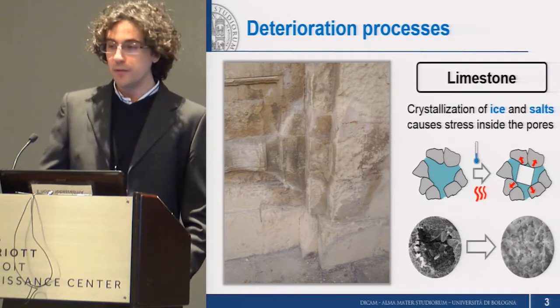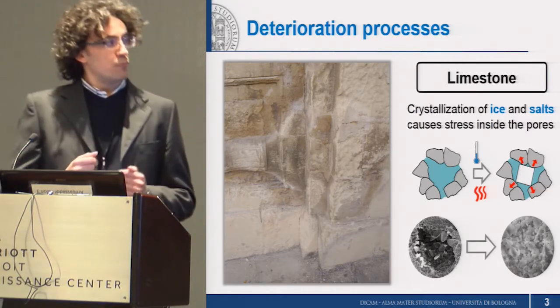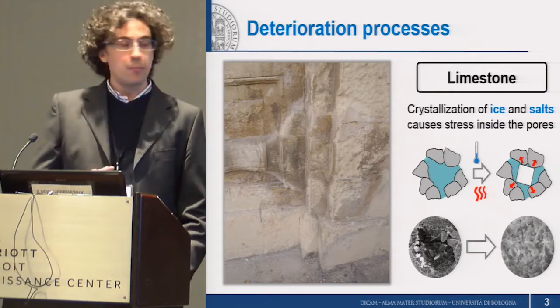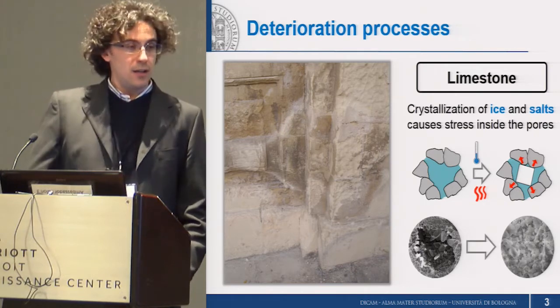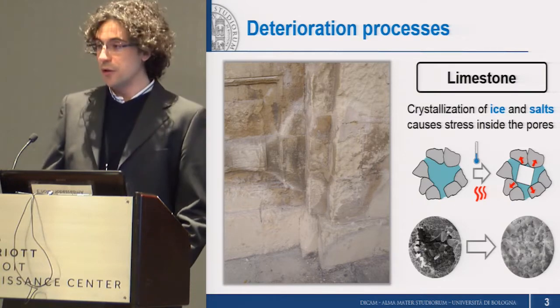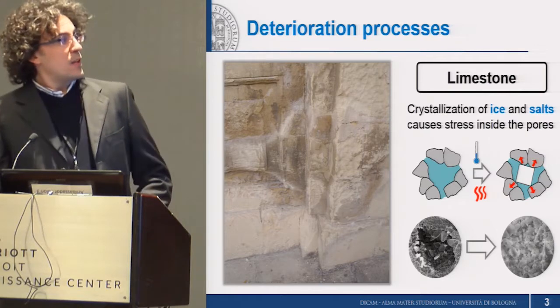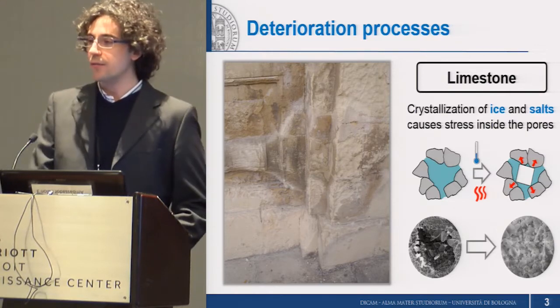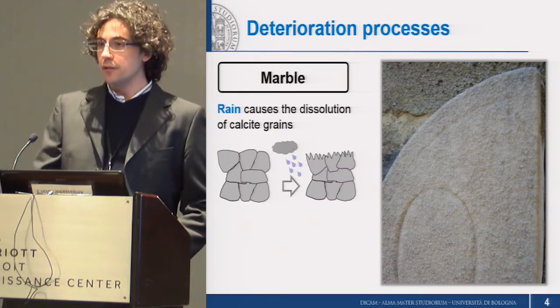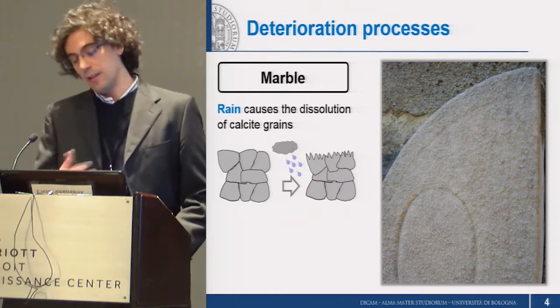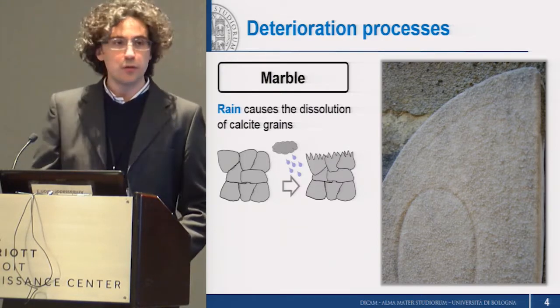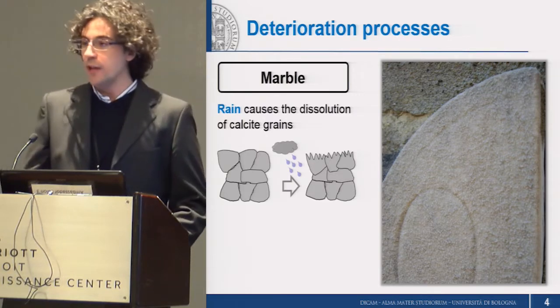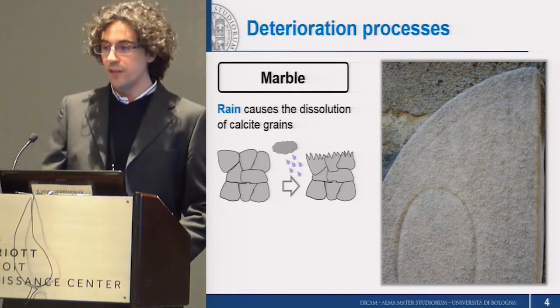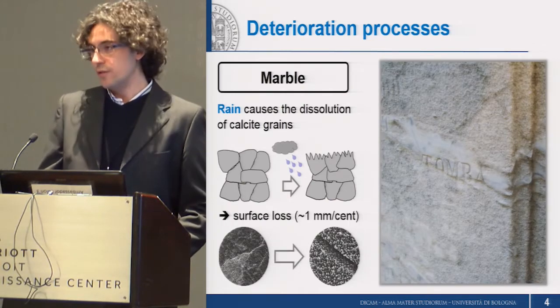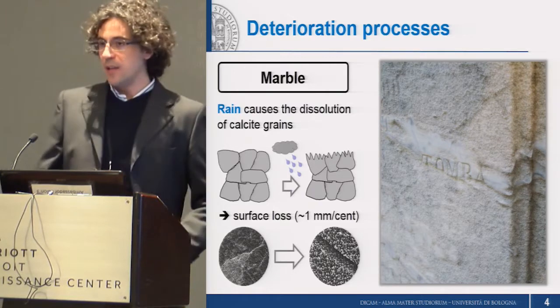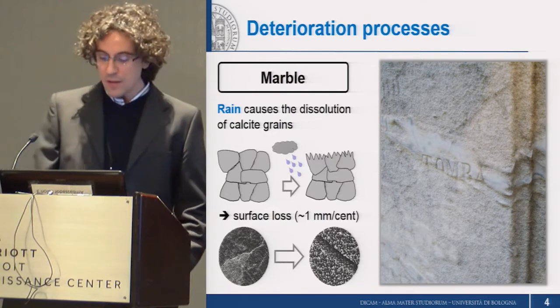In the case of porous limestone, the deterioration processes are more similar to those that occur in other porous building materials, such as concrete, so mainly stress arising from crystallization of ice and salts inside the pores. While in the case of marble, being non-porous, we have different deterioration processes. One is the so-called dissolution of calcite, the dissolution of marble, that arises from the relatively high solubility of calcite in water. And this is important because it can lead to a surface recession of a few millimeters per century, which implies a loss of carved elements on the surface of marble elements.